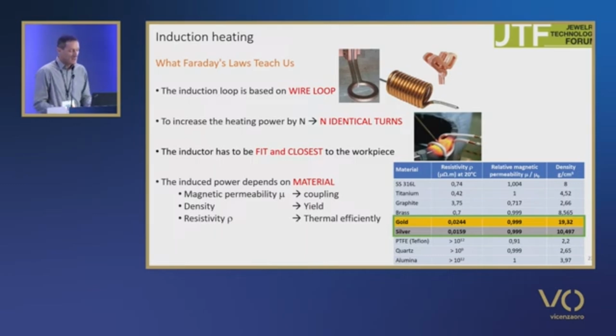As I explained, the induction effect acts at a distance, but it decreases very quickly with the distance. So the coil has to be as close as possible to the heating zone. And the induction effect depends on the materials. As it shows, stainless steel, titanium, and graphite are very good candidates for induction heating.